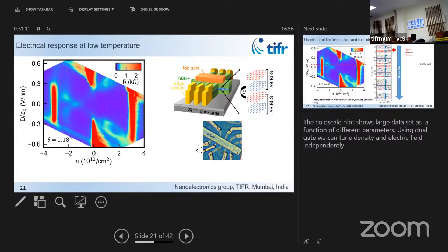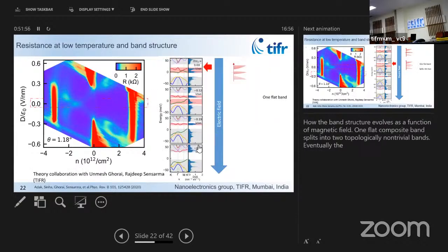We have 2 gate electrodes, one gate electrode here, another gate electrode here. This is one way to realize the gate electrode, but there are other ways. So what that does is that it provides an independent control of charge density in the device and electric field. So it's a very important distinction that charge density controls, in physics terminology, the Fermi energy or doping, and the electric field is an independent control. Because these materials are susceptible to this band structure modification because of the electric field, this is an independent knob that you have. So you can control charge density and electric field independently. Okay. So what you see here will become clear in a minute.